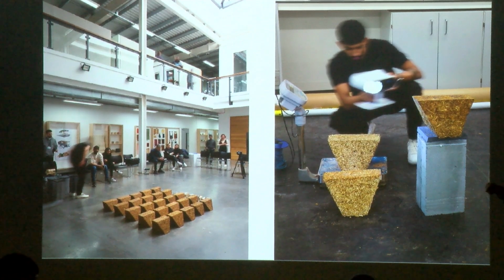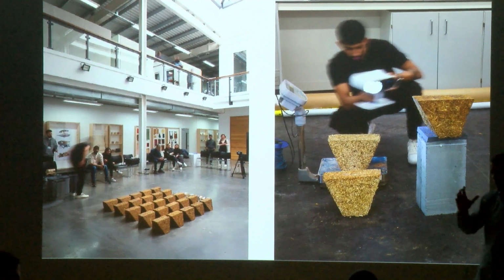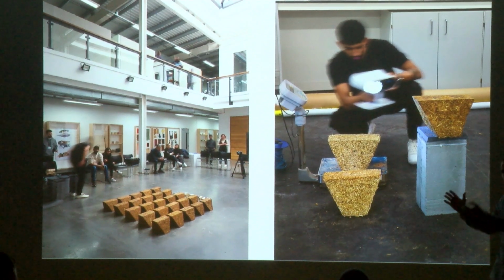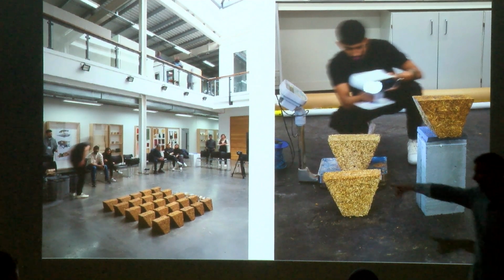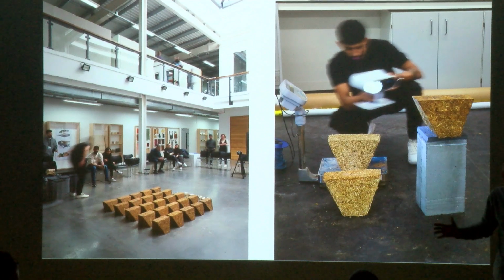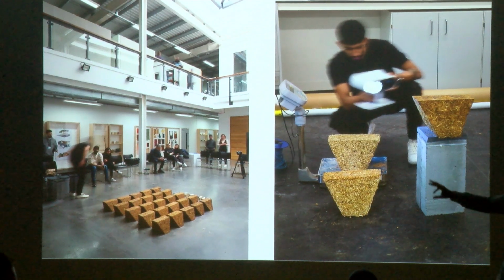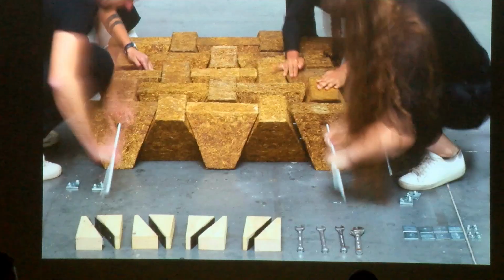And we 3D scanned all of them individually, one by one, and compared the volume after 2 weeks, after a month, after 2 months with the original 3D model. So we could assess how much shrinkage the whole system would have, which was fundamental to design a system where all the elements would come together equally. The reduction was between 5 and 10%, depending on the amount of binder that we were using, which was what we anticipated, but it was a very good use of 3D scanning technology to demonstrate how this slab would need to accommodate those tolerances.